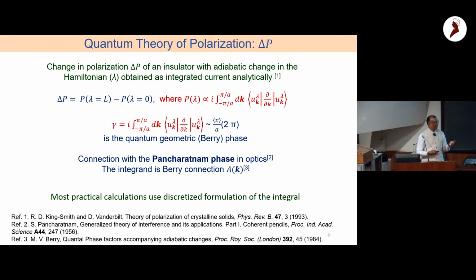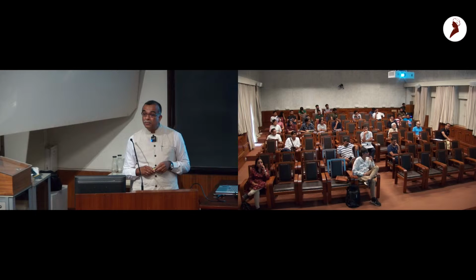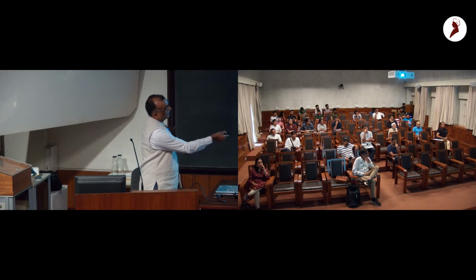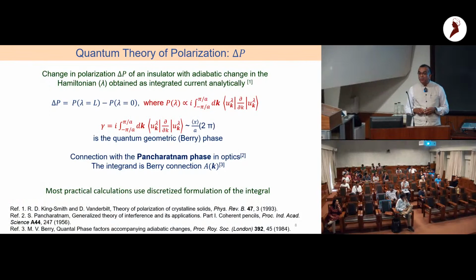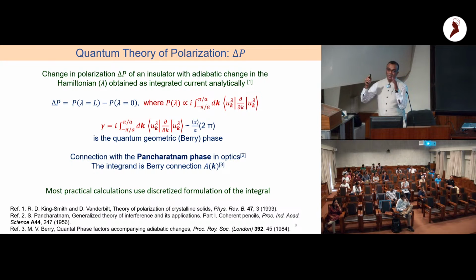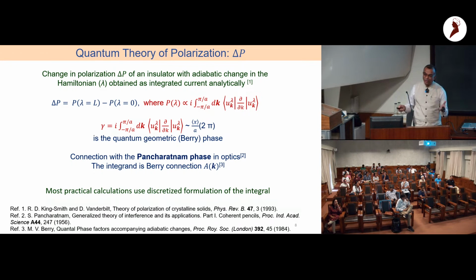No. See, this is defined at a specific lambda, right? So change in polarization is the polarization at lambda equal to 1 minus that at lambda equal to 0. For a permanent polarization system, if you have a state with zero polarization, which is a centrosymmetric state, you can estimate absolute polarization using this formula again. I wanted to say that you can only measure change in geometric phase. No. Geometric phase is calculated absolutely. If I can measure, then I measure. See, geometric phase, because it's a phase factor, is defined modulo 2 pi. But otherwise, you can calculate it at any lambda. So I'm saying from there we can measure polarization. No, the point is, when you want to interpret geometric phase as a measurable polarization, you need to be careful.